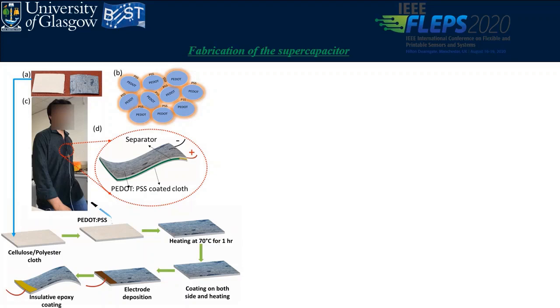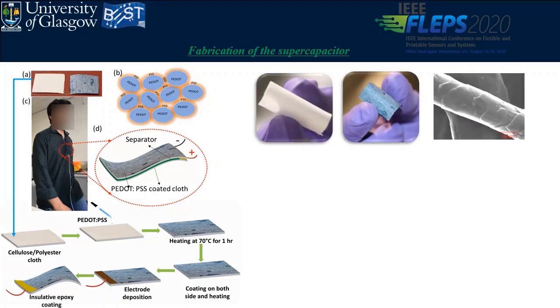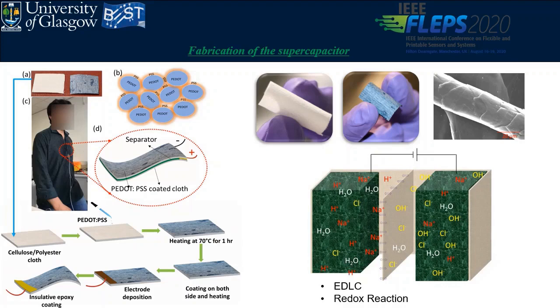PEDOT:PSS is an excellent conductive polymer, and here you can see the pure cellulose cloth, then the cloth coated with PEDOT:PSS, and the SEM image of one of the fibers of the cloth where the material is strongly adsorbed. And when the electrolyte comes into contact with these two electrodes, we have a stacking of two electrodes. As you can see in the slide, the fabrication steps are the single electrode fabrication and stacking of such electrodes with cellulose polyester as a separator.